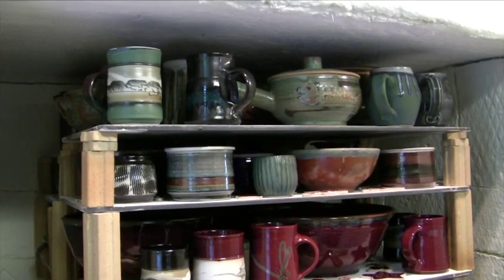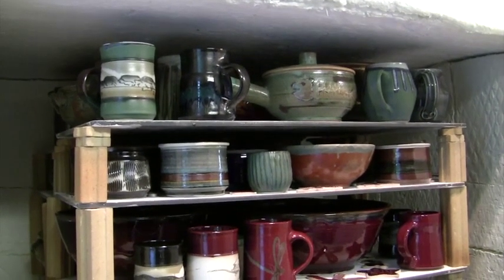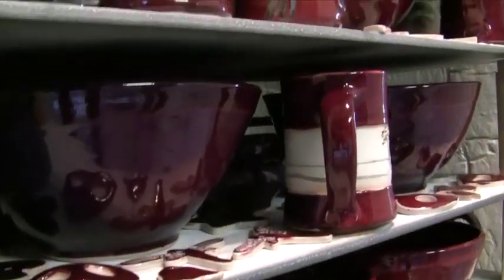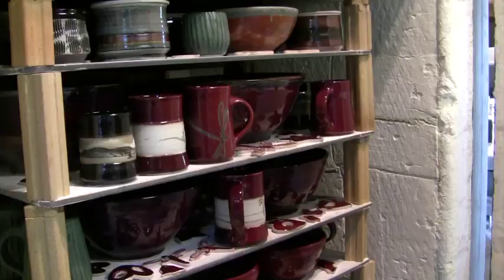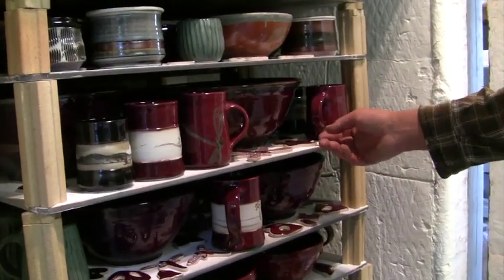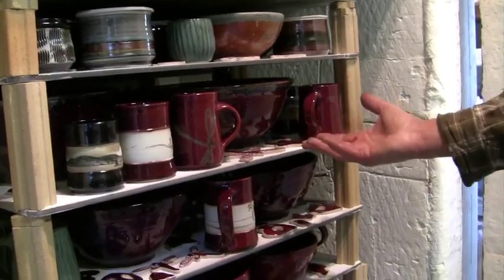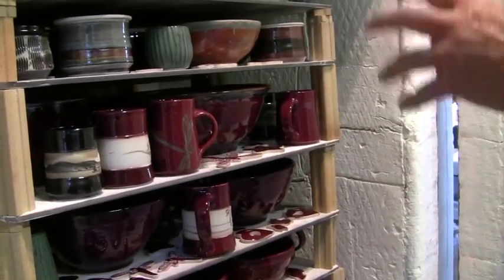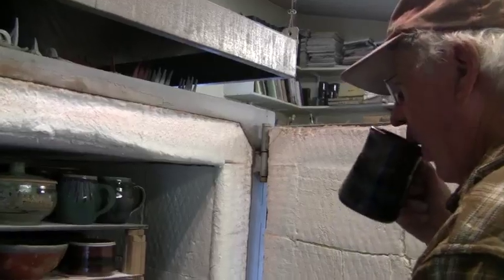You have to think a little bit about where you put stuff. Yes. The red likes to be out in here. That's why I make Rachel do these ornaments, because it creates the atmosphere so that all this copper atmosphere will create the red there. So if I don't have the ornaments, it doesn't come out as nice.